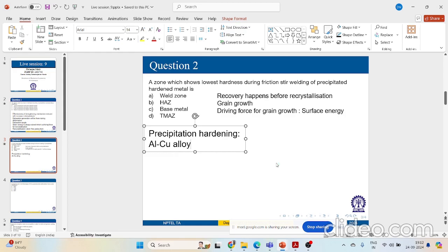Now, the strengthening precipitates that will be forming get destabilized or dissolved in the matrix above a certain critical temperature, depending upon the composition, right? Those will be dissolved with increase in temperature. There will be a certain temperature above which you will see there is no precipitation formed. So there will be this reversion or dissolution of those precipitates. Now, formation and dissolution of those precipitates always affect the hardness and strength of your metal during welding.